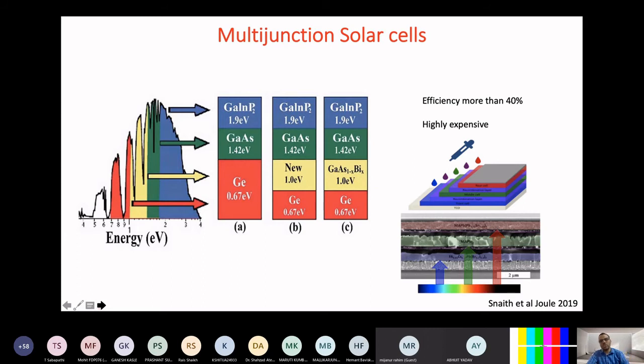So you make multi-junction solar cells, and this is the solar spectrum in terms of energy. You try to absorb each and every component of the solar spectrum by utilizing various kinds of semiconductors, as low as germanium with 0.67 electron volts, then gallium arsenide. So this is a three-junction, triple junction cell. These are four-junction solar cells. These four-junction solar cells are being used, and they can give efficiency as high as 45%, close to 40 plus. So you are generating a good amount of energy using these semiconductors, and that is the way to ensure that we can meet the constant energy requirement.